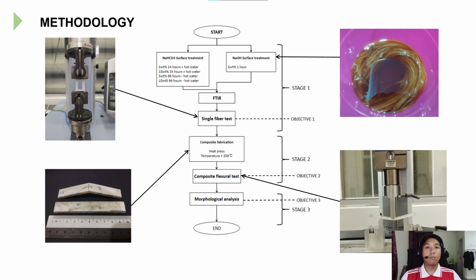After that, the composites are fabricated using the pineapple leaf fiber and polyamide 11, or PA11. This is at 200 degrees Celsius using a pressure of 7 bar, where the composite is then cut to be used for flexural testing. Finally, we have morphological analysis using SEM to see the surface of the untreated and the treated fibers.